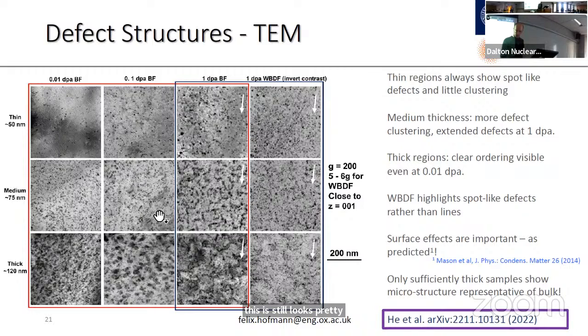By the time you get to 0.1 dPa, you start to see the emergence of some extended structures. Yeah. By the time you get to 1 dPa, you can definitely see some extended networks that are there. And if you move to an even thicker region, so this here is 120 nanometers thick, you have visible defect self-organization, even at very low dose, even at 0.01 dPa. So I was really surprised when I saw this, because what it really says is you need to be super careful that the foils, the samples are thick enough that your damage actually is representative of what is presumably there in the bulk. Yeah, because your surfaces do have a pronounced effect.